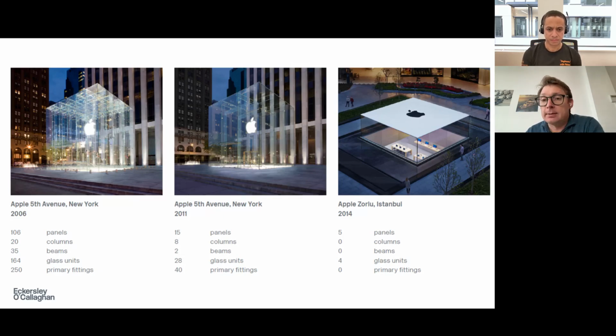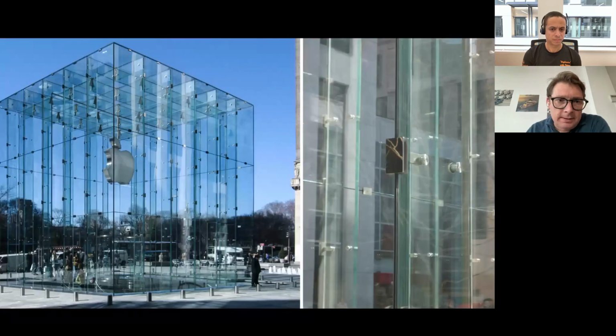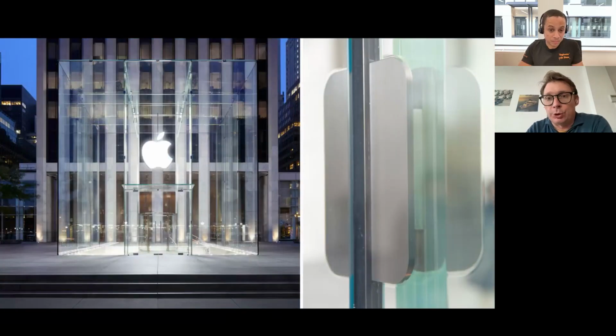So we laid the wall panels on their side, and we actually used a carbon fiber roof to span between the glass walls and provide the lateral stability. So you can see the difference between quite a fitting heavy structure, although I quite like the fittings, where you can see the function of the glass and what the load paths are, to something that's much more transparent, and the fittings are doing everything, so it's a bit more difficult to discern what they're doing.